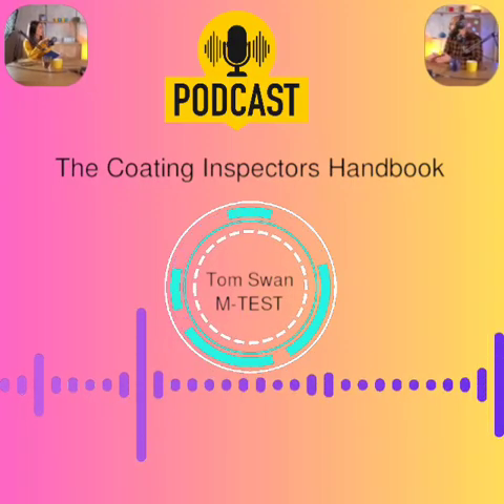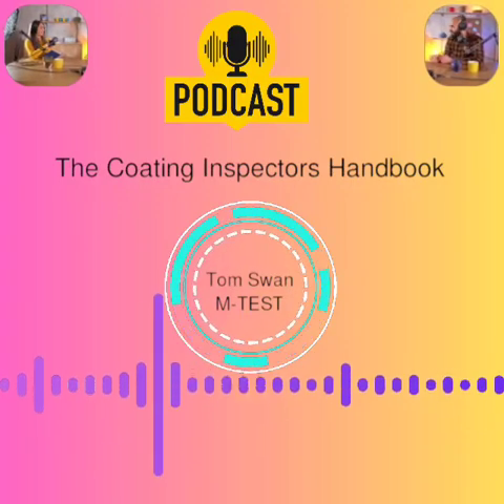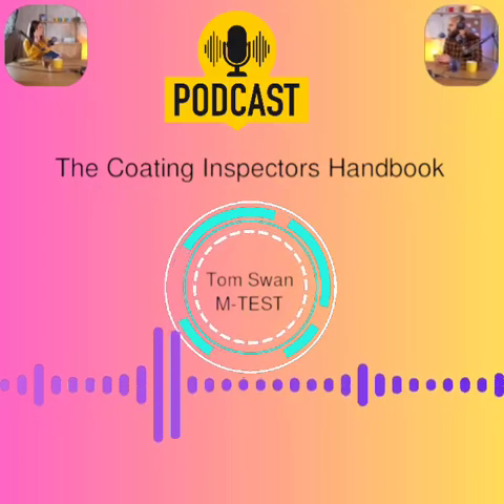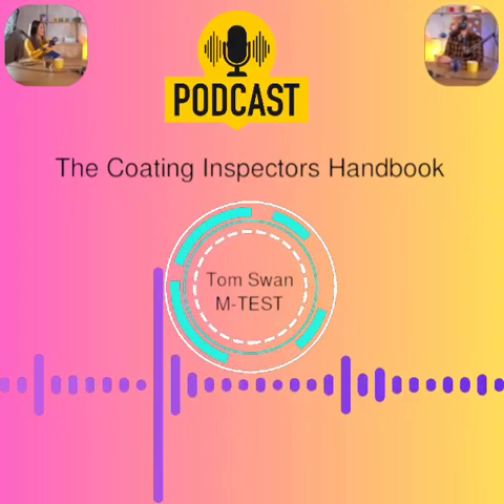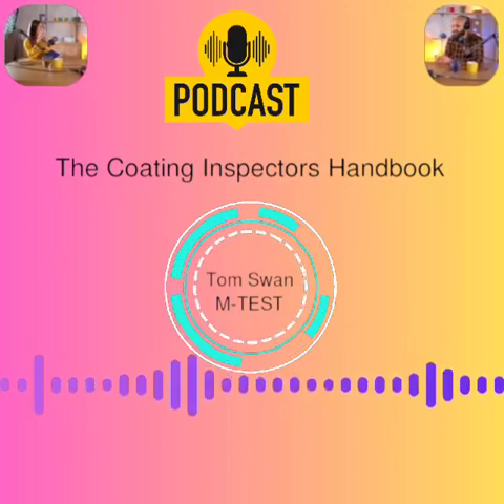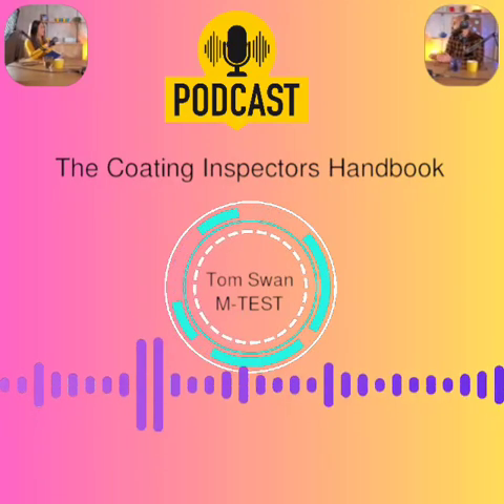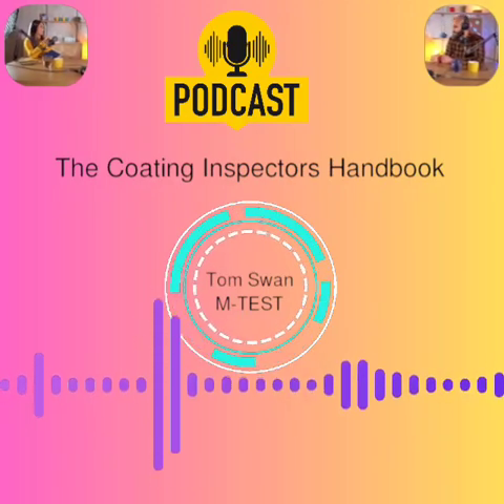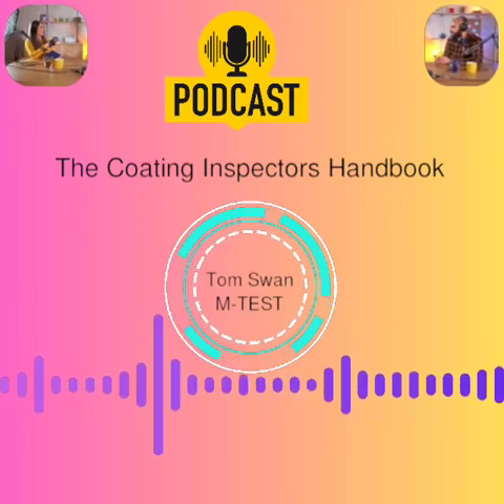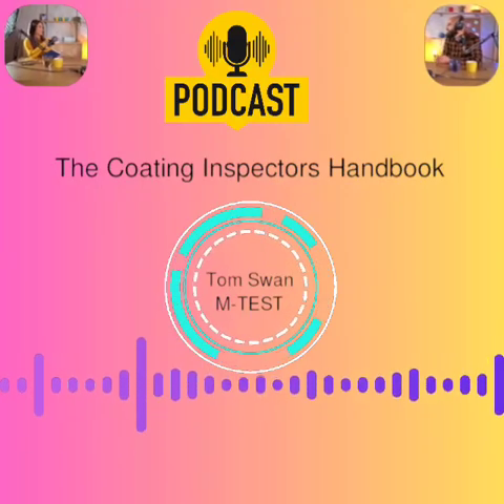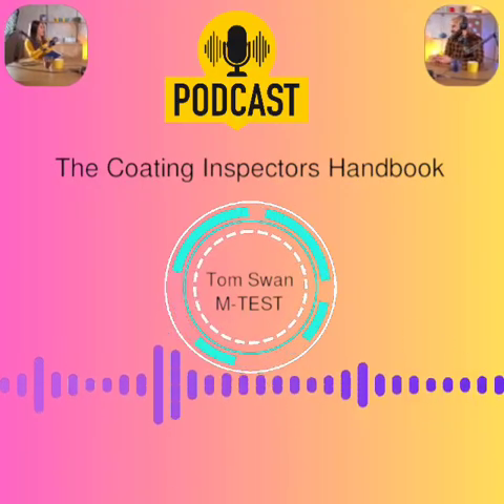You should get a signal. Setting the voltage on concrete: you can't use steel settings, you need higher voltage, and it might vary. Best way: create test holidays and find the minimum voltage needed to spark at different distances from ground. If voltage climbs further away, you need a higher test voltage or more ground points. Conductive primers make it much easier, like testing on metal. Are these testers dangerous, the high voltage ones?